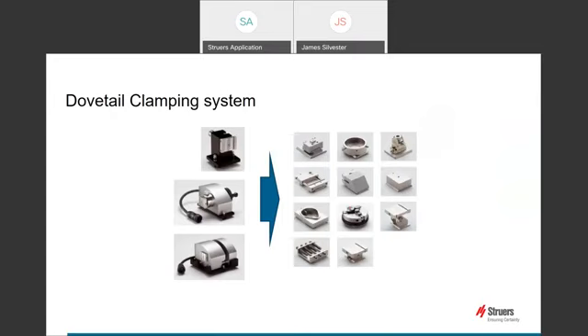These clamps have been developed to be used similarly to qualified tooling as you find in a CNC profiling machine. What this means is that your small sample can be clamped up away from the machine and inserted into the dovetail fitment. When satisfied that the sample is held securely, the dovetail clamp and sample is attached to the machine for cutting. This gives large benefits when cutting similar parts over and over, as additional clamps can be set up as one is automatically being cut and exchanged quickly for an almost continuous throughput.